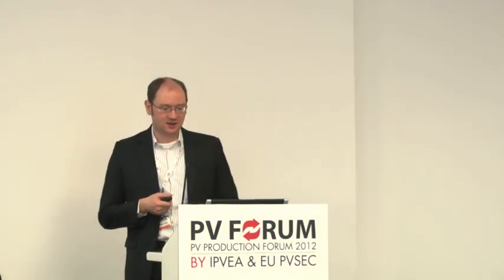The precursor for these layers is trimethyl aluminium, which is then reacted with an oxygen source, which can be nitrous oxide or moisture. Trimethyl aluminium is a very common molecule in optoelectronics and semiconductor applications, but it is a new molecule for the solar industry. It is a pyrophoric liquid, which means it ignites spontaneously in contact with air. So a safe delivery of the molecule to the point of use is key to enable the adoption by the industry. Backside passivation has shown in pilot runs to be able to improve cell efficiencies by 0.5 to 1% absolute level.